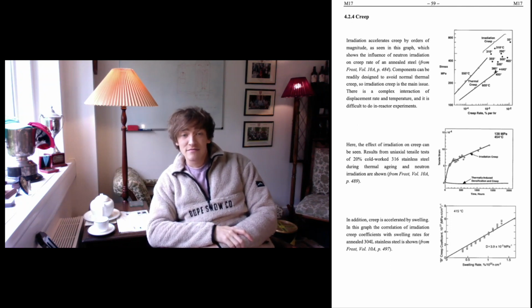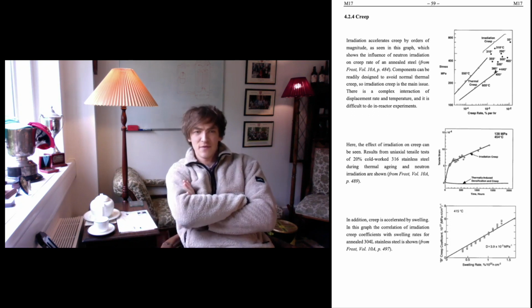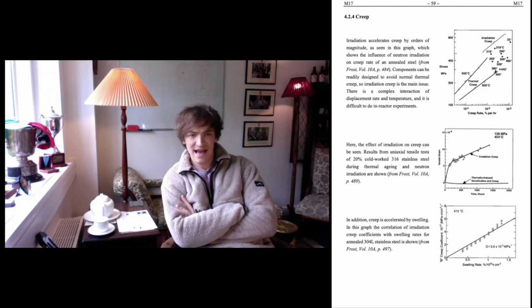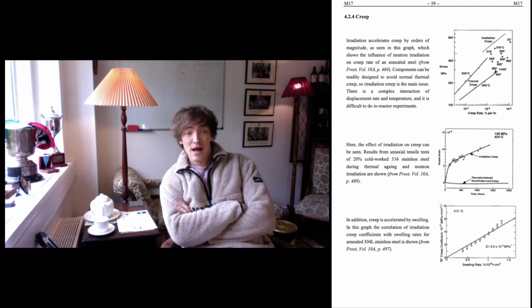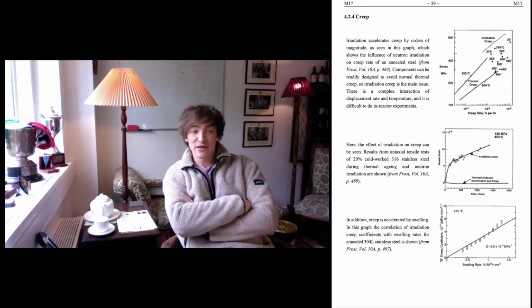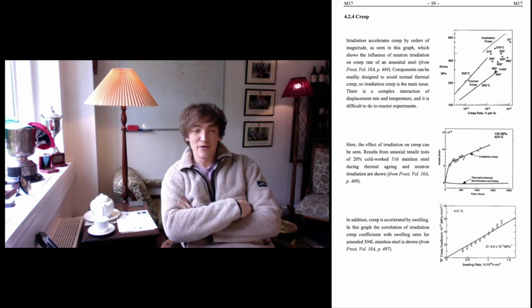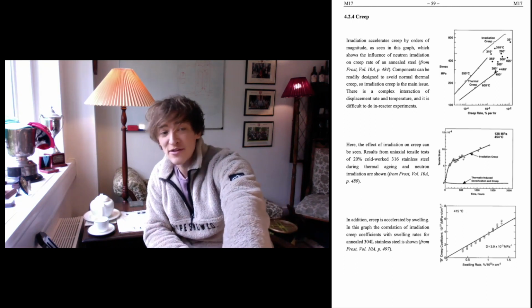Not only that, but creep is accelerated by swelling, as shown in the graph to the bottom right there, with swelling rate on the x-axis and a creep coefficient on the y. So it's very similar, the effects of creep. The key point is accelerated by swelling. But you can read up on that further. That's about how much we really need to know for the time being.